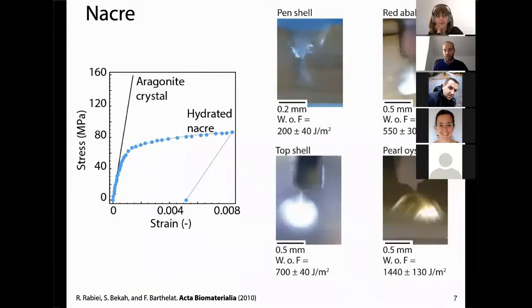Besides the pictures, if you look at the properties of nacre, this is a stress-strain curve in bending. What drove people to this natural system is that when you start testing it, you see something very interesting. For something that is almost a ceramic, a pure crystal of the same mineral, you can see it's very stiff, but it's extremely brittle. When it reached the maximum strength, it just snapped.